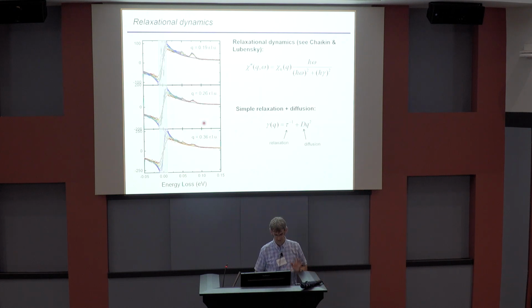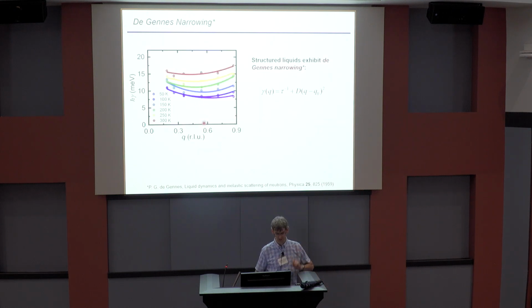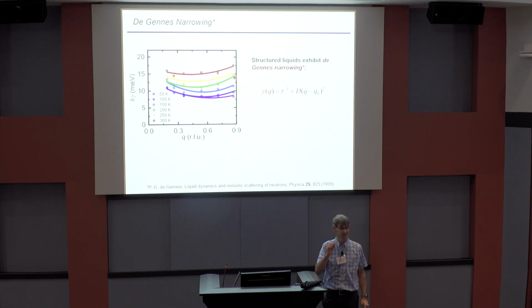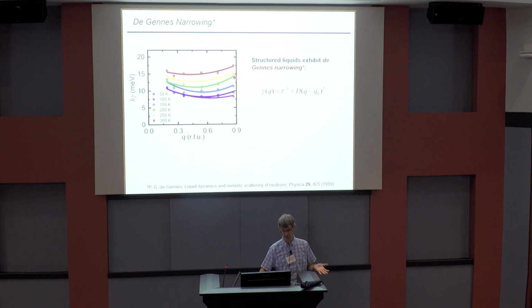So the weird thing is, in this strange metal, we see such a minimum. And what it suggests is that the low energy dynamics in this strange metal state arise from some finite objects that are colliding off of one another. And the flow is dominated by sort of the steric interactions between these things. And you can estimate their size by looking at the inverse of where this minimum is. So let me just show you the fit.